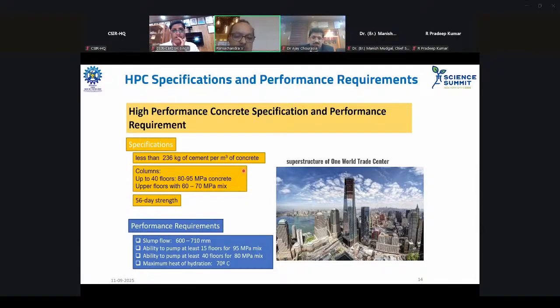There were performance requirements like the slump flow was fixed at a minimum of 600 mm, and the ability to pump at least 15 floors. Pumpability of concrete was very important, and maximum heat of hydration was also fixed.